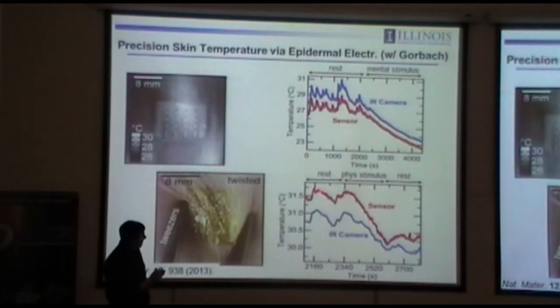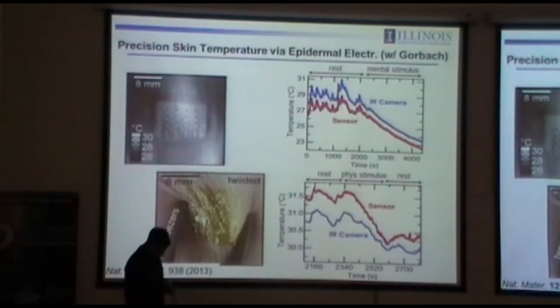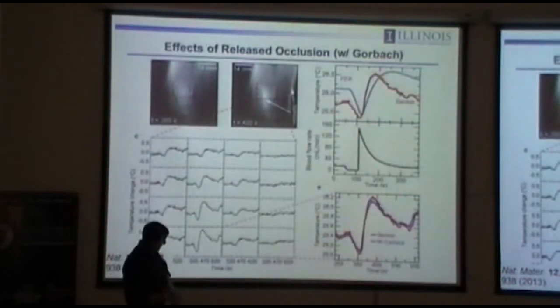Here's another example. Perfect agreement between IR camera and sensor. Rest, you see these oscillations again. Now, this corresponds to physical stimulus, which you might expect based on that movie I showed you would cause sweating and a decrease in temperature. You see that. And then once the exercise starts, you kind of have a fixed temperature down here. Now, the physical stimulus is what's interesting here. So we have a device on the left wrist, and the physical stimulus corresponds to rubbing two fingers together on the right hand. So you're rubbing your fingers here, and you can pick up a temperature change over here. So very, very precise measurements, and you can see all kinds of subtle things that could be very important.